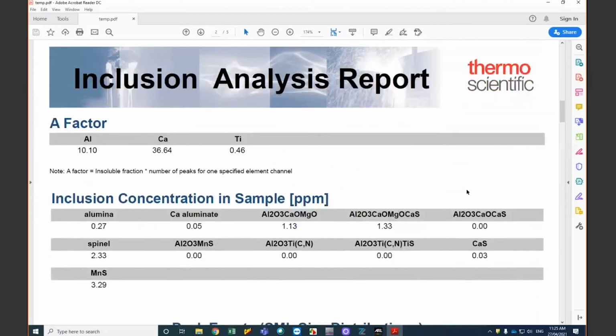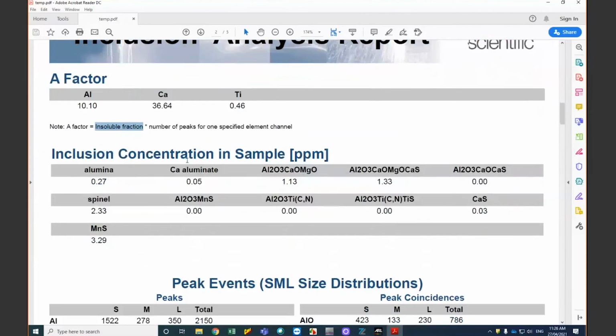Then you have another field called a factor, where this factor is one parameter suggested by some European steel makers. According to them, this can be used as the cleanness index for process control. This factor is defined as the insoluble fraction multiplied by the number of peaks for one specified element. So that means this parameter is not only considering the peak count for each element, but also the size of the inclusions, because the size of inclusion relates to the insoluble fraction, the intensity level. So when you have a bigger size, you will have a higher intensity level, and that is calculated in this part. So that is one parameter.